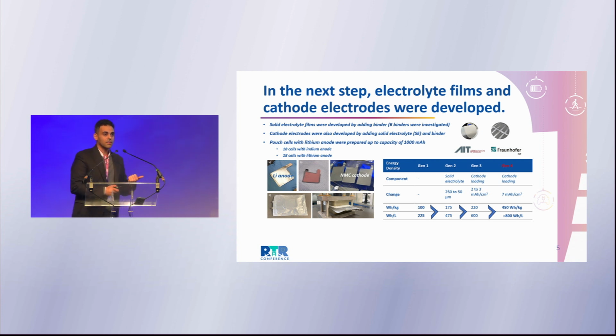So we took this solution, we said, okay, we need more time to focus on lithium metal anode. Meanwhile, we continued with solid electrolyte and cathode. And as you can see, for example, in the picture, AIT has developed a solid electrolyte film in this project. It's a freestanding solid electrolyte layer. They tried many different binders, many different solvents to come to this final product. Then cathode electrodes were fabricated by Fraunhofer IST. They also optimized the process to be able to upscale these electrodes.